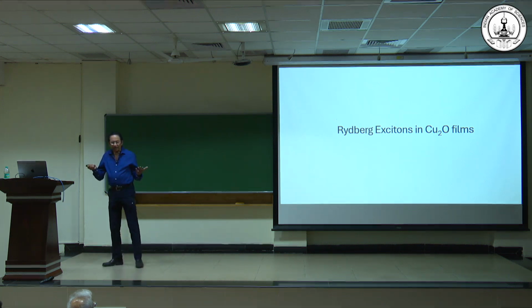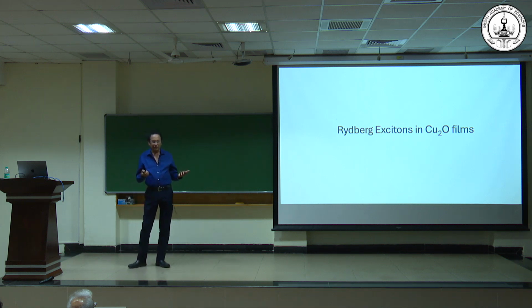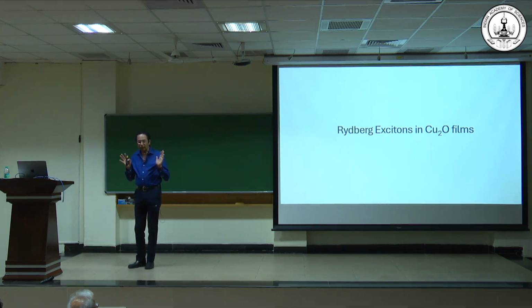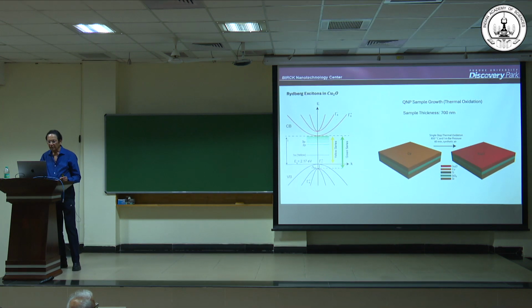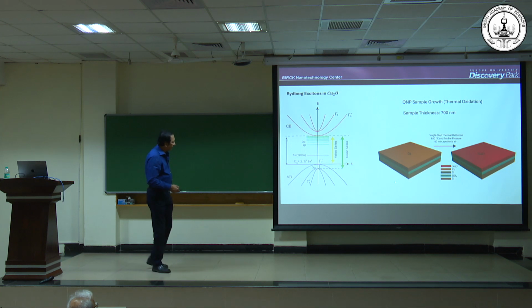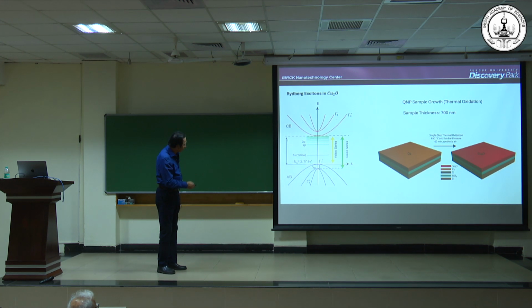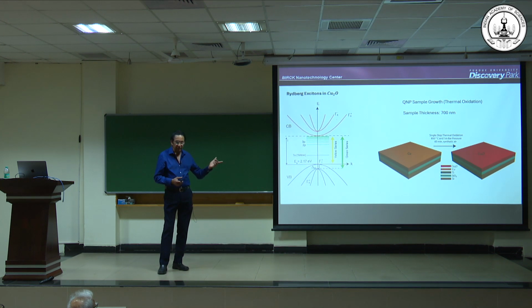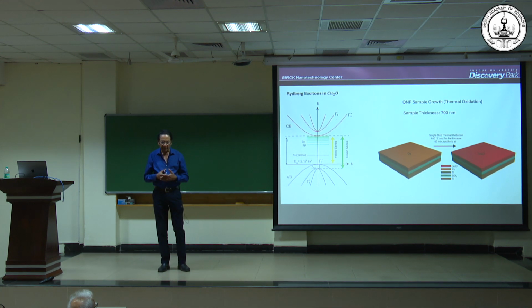So what solid has that kind of a property? Do we have some solid which has got that kind of a thing? It turns out cuprous oxide is very interesting. Cuprous oxide is a material in which you have an exciton, and the exciton has a very large binding energy, almost like 100 milli electron volts from the bottom of the conduction band. Okay, so that gap is so large that we can look for Rydberg states in excitons. So people have now seen, in single crystal cuprous oxide, it's a mineral found on Earth, actually, you can get it out, people have found Rydberg states up to 35. It's really remarkable. At 35, the Rydberg radius is like several microns, and it's huge, right?